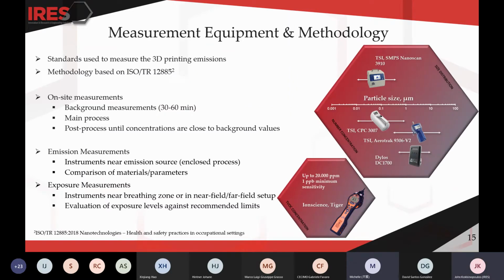Okay, now regarding the methodology we are employing, it is based on the ISO for nanotechnologies and health and safety occupational practices. In this approach, on-site measurements make up the core of the assessment. Measurements can be described in three parts: before the start of the process, we record background concentrations for about 30 to 60 minutes, and later use them as a control against which the other values are evaluated. Next, concentrations are measured during the process and after its completion until the values return back to the background levels.